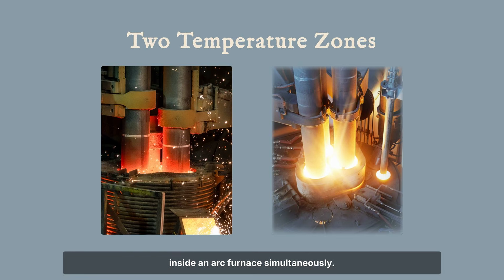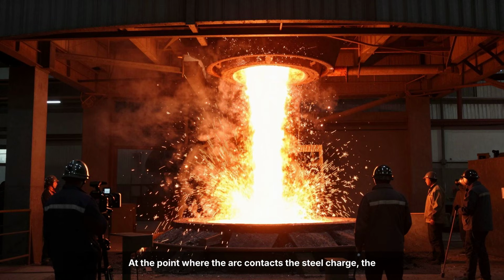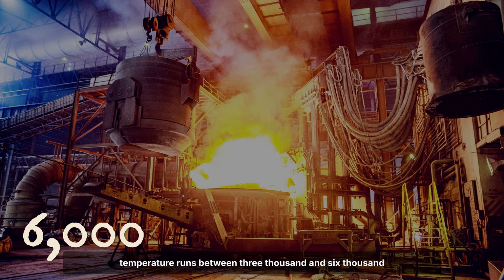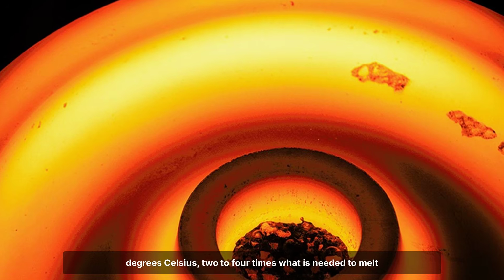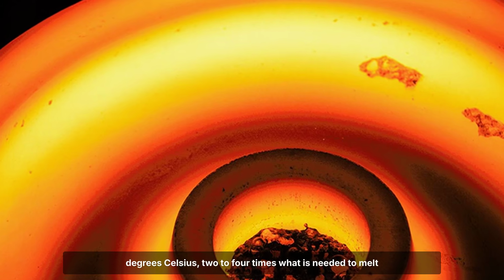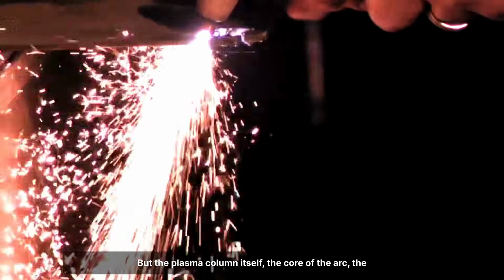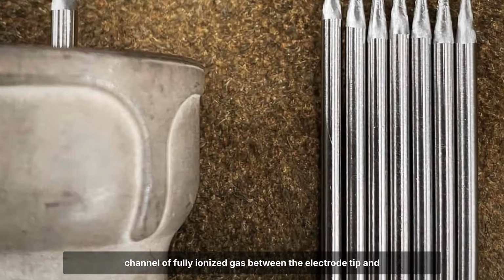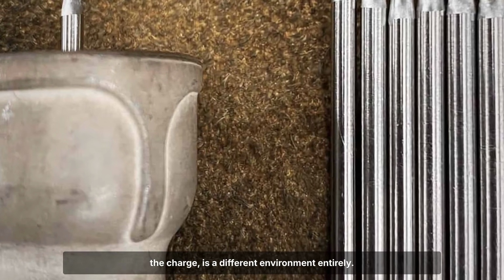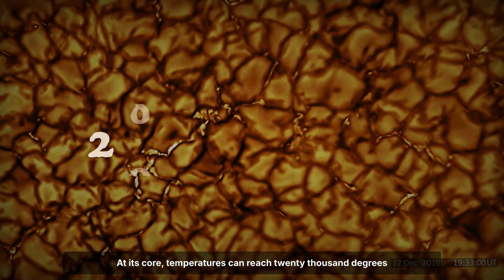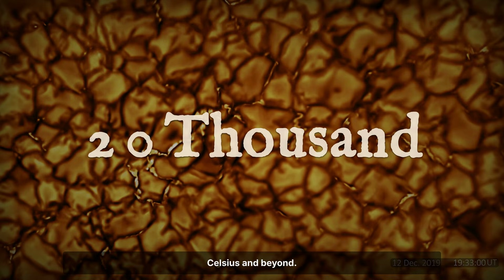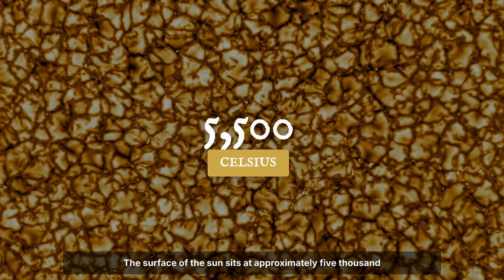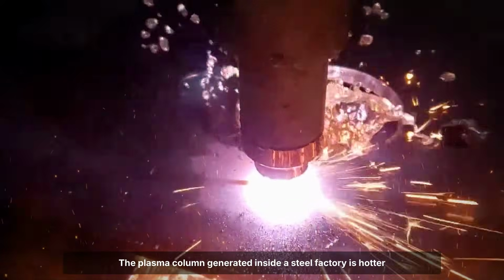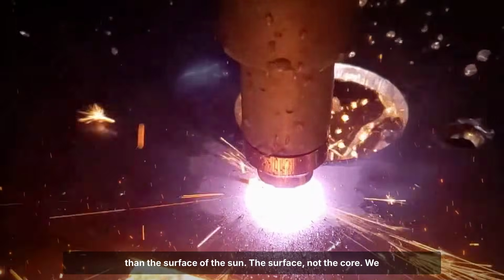There are actually two different temperature zones happening inside an arc furnace simultaneously. At the point where the arc contacts the steel charge, the temperature runs between 3,000 and 6,000 degrees Celsius, 2 to 4 times what is needed to melt steel. But the plasma column itself, the core of the arc, the channel of fully ionized gas between the electrode tip and the charge, is a different environment entirely. At its core, temperatures can reach 20,000 degrees Celsius and beyond. The surface of the Sun sits at approximately 5,500 degrees Celsius. The plasma column generated inside a steel factory is hotter than the surface of the Sun.